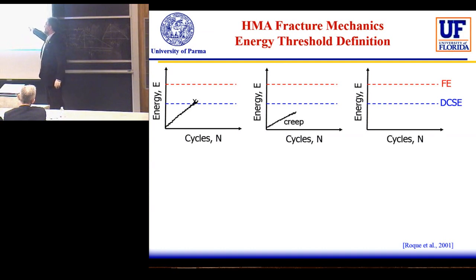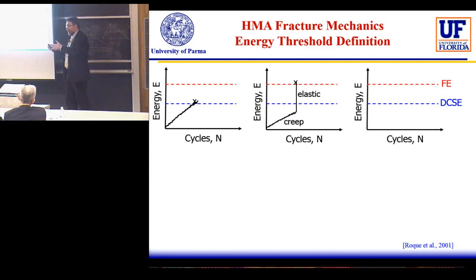If the energy is below, you have nothing, and the micro crack can be healed. But if you have one pass, one load that involves the elastic part of the behavior of the material, you can go above the other threshold, and again you can have a not healable crack. But if you stay below the dissipated creep strain energy and below the total fracture energy, you have no cracking that appears. So you have some micro cracks, but the healing property of the material can seal or repair the material.